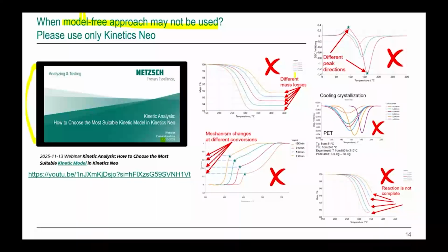And here are a couple of slides which show where model-free kinetics may not be used. For example, if you have different values of a total mass loss or different values of peak areas for different heating rates, then you have competing reactions. Model-free approach doesn't work. If mechanism change is not always at the same value of conversion, then model-free approach cannot be used. Actually, here, these curves, they are not simulated curves. They are real experimental curves, what I show here.